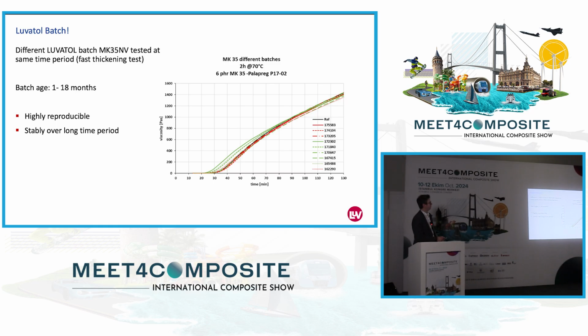So for example, here's our MK35NV. We made lots of batches for different countries, for different customers. And we adjust the Luvatol during our production so that you always have the same thickening effect, that you always get the same result. And at the end, it's not a calculation of powder versus paste. It saves you time, which you normally need to adjust the powder all the time. It saves you cost, because at the end you can use more of your SMC. And it gives you more security that you can, of course, hold your promises to your customer.